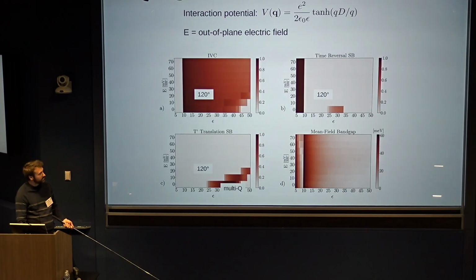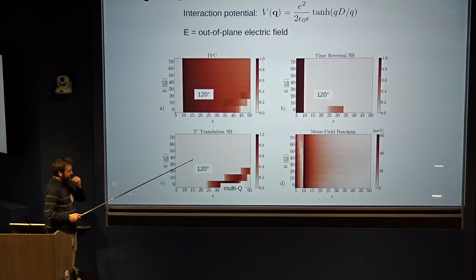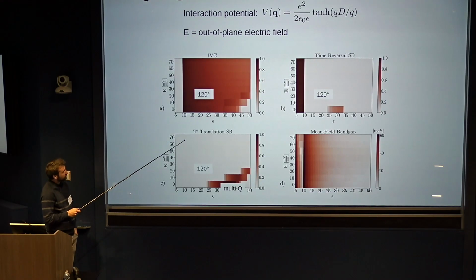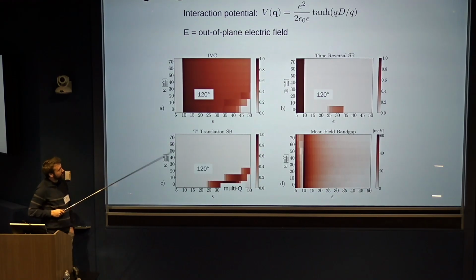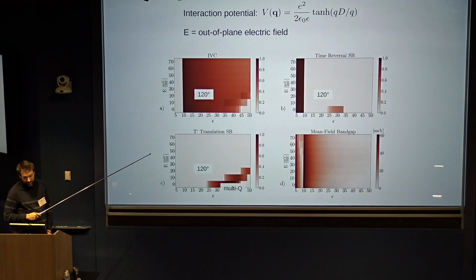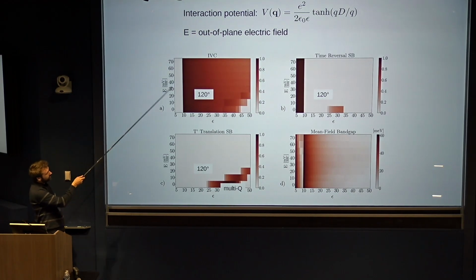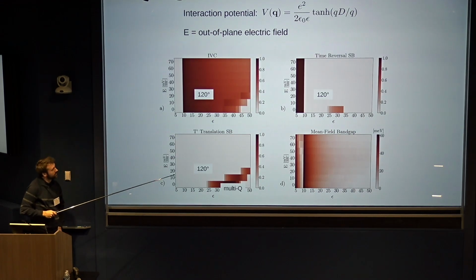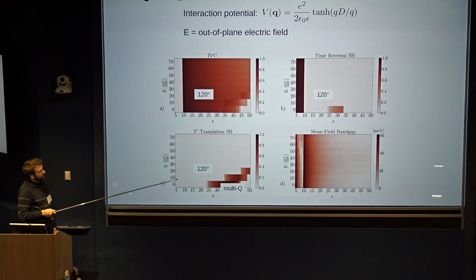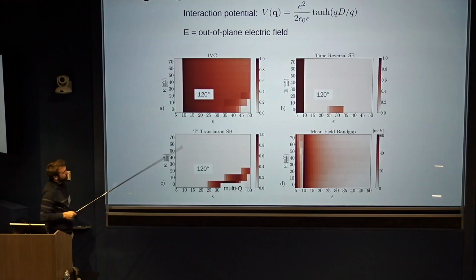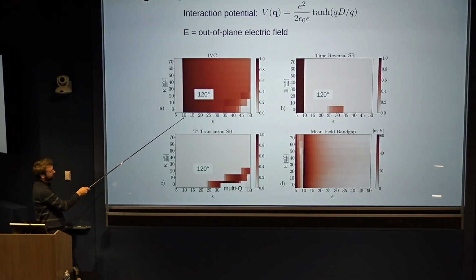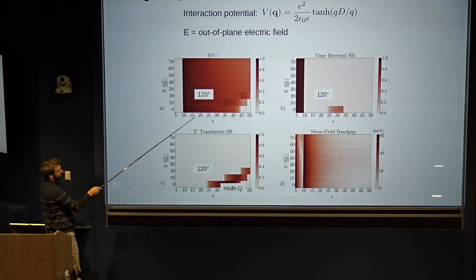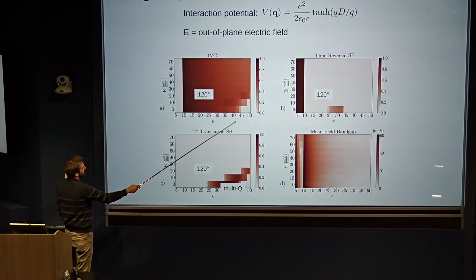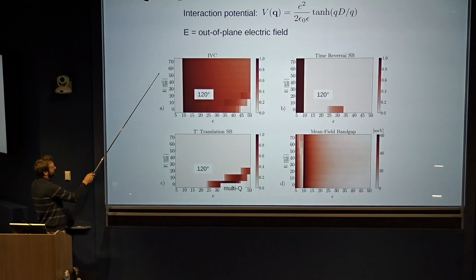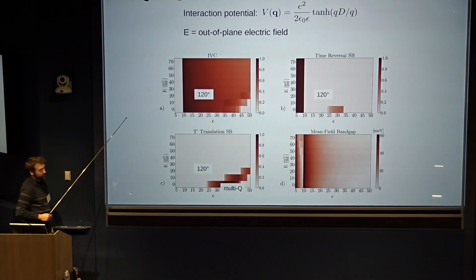Now, where did we find it? We did a 2-dimensional parameter scan. The interaction we added to the continuum model was this gate-screened Coulomb interaction. The potential in momentum space is written on the top of the slide. D is the sample-gate distance, and what we varied is the dielectric constant epsilon, shown here on the x-axis. Going to the right, the bigger dielectric constant means weaker interactions, and the y-axis is the other parameter we varied, which is the displacement field.